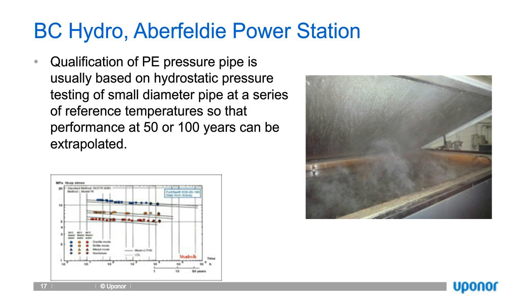So when polyethylene is tested at reference temperatures of 23 C or 20 C, and I state the two temperatures because the reference temperature in the North American standards is 23 C, and in the ISO standard it's 20 C, the failure is usually ductile, and that means there's a ballooning of the pipe wall. And the data points, if you get a significant number of these, can be extrapolated to times of 50 or 100 years as desired. And then factors of safety are applied to these extrapolated values. Typically, it's the inverse of the factor of safety; we're using a design coefficient. In the ISO part of the world, they would typically use 80% of this extrapolated value, and we're more conservative in North America. We'd use about 63% of that.